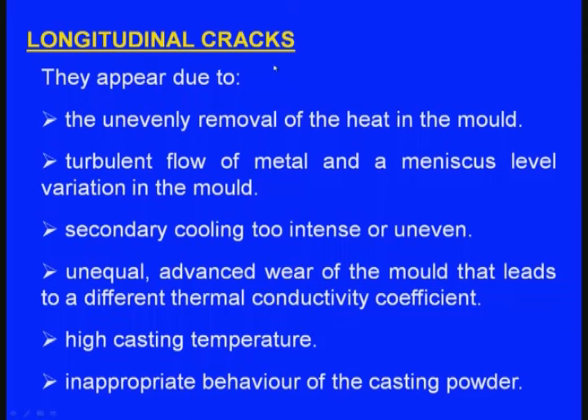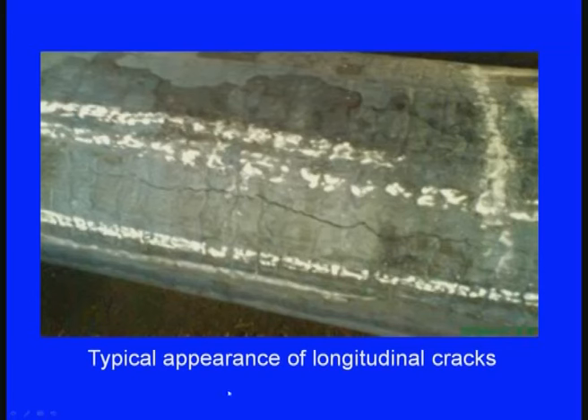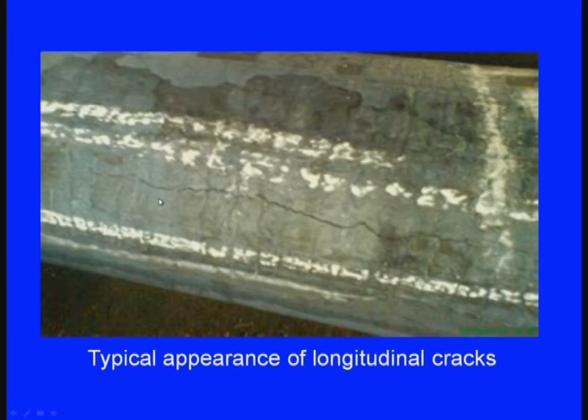The next defect is longitudinal cracks. They appear due to uneven removal of heat in the mold, turbulent flow of the metal, meniscus level variation in the mold, secondary cooling being too intense or uneven, unequal advanced wear of the mold leading to different thermal conductivity coefficients, high casting temperature, and inappropriate behavior of the casting powder. Longitudinal cracks are parallel to the axis of the bar — this is the typical appearance.